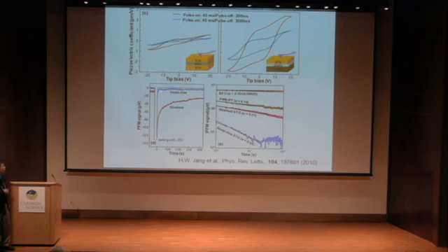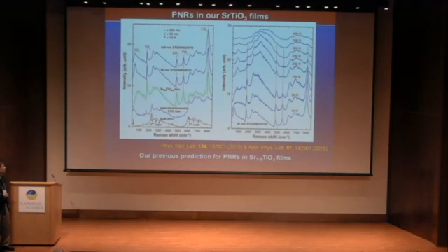And for the relaxation here, we can see that bismuth ferrite doesn't relax at all over a long period of time, and the strain-free one relaxes much faster than the strained film. So we looked at this by Raman. This strain-free strontium titanate is grown from a strontium titanate single crystal target, which does not have a clear indication of ferroelectricity.